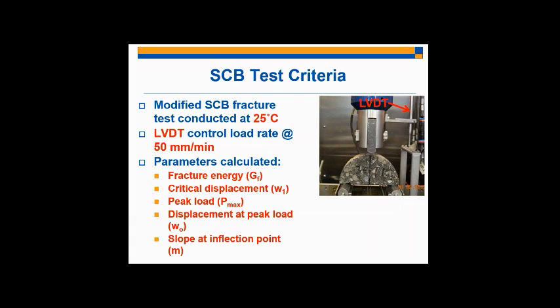You have the peak load, which is simply the maximum load that your specimen experiences during the test. You have the displacement at the peak load, so whatever displacement your vertical transducer is experiencing at the peak load. And then you have the slope at the inflection point, the first inflection point past the peak load. And we call that M, basically.